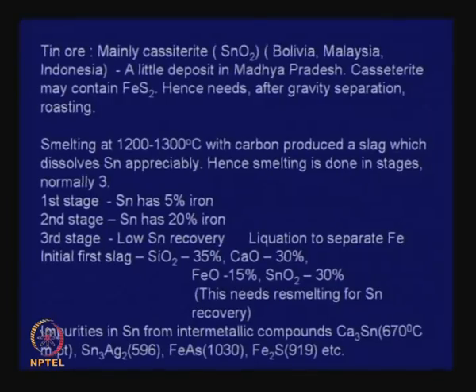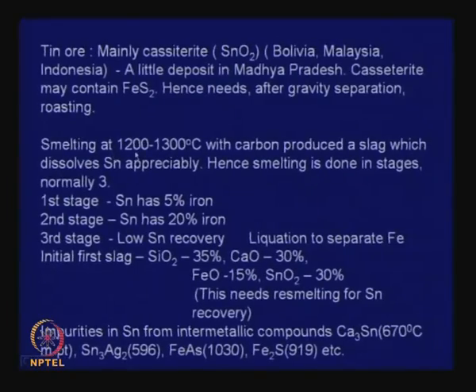Tin dioxide will not be reduced by carbon in one go. The idea is that we will do that in stages. Why will we do that in stages? Let me explain. In the smelting at 1200 to 1300 with carbon, we first try to take out some amount of tin. Iron is also coming. We do not want to take too much tin out, because if we want to take too much tin out, then too much iron will also come out. So, the aim is to have tin dioxide reduction incomplete in the first stage and produce a metal with 5% iron.